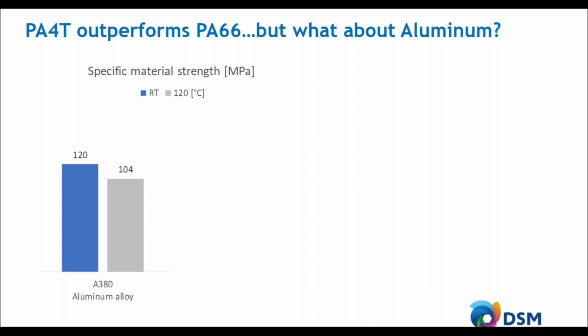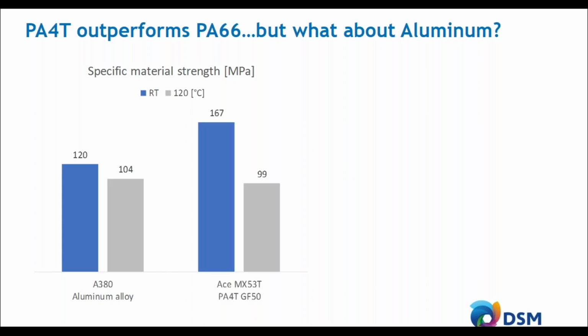So as a short recap, PA4T outperforms polyamide 6,6. But what about aluminum? Is it really as good as aluminum? What you see here is the performance of an aluminum alloy at room temperature in blue and 120 degrees C in gray. And what we did is we divided the tensile strength of this material over the density. And then you get the specific material strength. But what about PA4T? If you look at the specific material strength of polyamide 4T with 50% of glass, you see that at room temperature it actually outperforms aluminum. And at 120 degrees C, it is on par with aluminum, meaning that these types of materials can be used to replace aluminum.